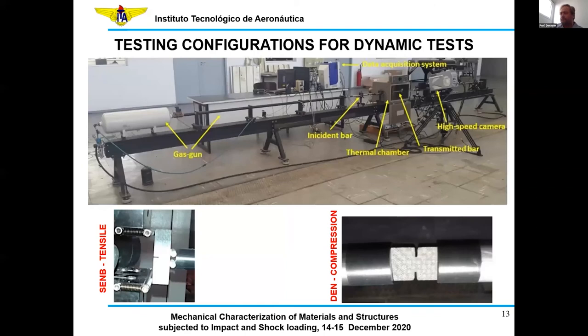And then the dynamic tests we perform in a split Hopkinson pressure bar available in the aerospace structures lab at ITA. Here I show you some details of our bar. We have a gas gun here, incident bar placed there. We also have a thermal chamber that allows performing tests at different temperatures, going from minus 54 up to 100 degrees. We also have a high speed camera that allows acquisition of images during the fracture process. And the transmitted bar is a little ahead here from the thermal chamber.